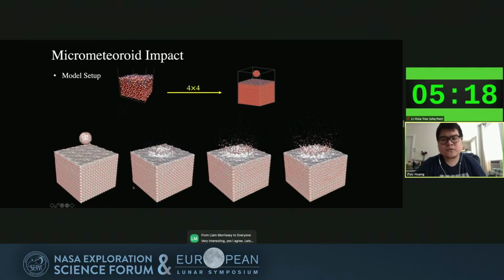And then we move on to micrometeoroid impact. We keep the implanted samples from the previous simulation and then replicate them in the X and Y directions by 4 and 4. Then we place another silica sphere on the top and then assign an impact velocity to it. The snapshot shows the bottom; we created the surface by the alpha shape method, and we can see the mini crater formation as well as some molecules and atoms being ejected from the surface.